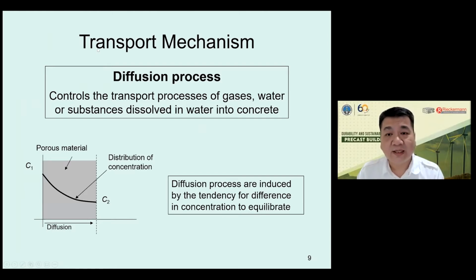We can calculate the degradation process, and the underlying equation is the diffusion process, but I will not go into detail about the diffusion process. But diffusion means that there is a difference in concentration. So the outside concentration is higher than the inside concentration. Therefore, the material will move. The outside concentration could be acid concentration or salt concentration, and it will move inside the concrete and then cause degradation in the concrete.